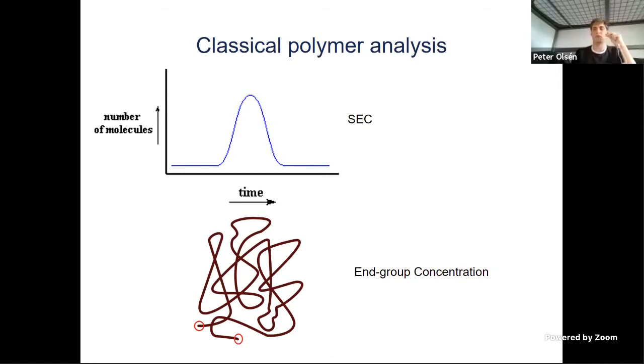So if we connect these, the question here is what is actually happening with the degraded matrix polymer during compounding and its relationship to the initial moisture content in the fiber. When we do a polymer analysis, the two main methodologies we use are either SEC, size exclusion chromatography, looking at the molecular weight distribution of the polymer phase, or NMR, looking at the end group concentration in relationship to the repeating unit. These are two very powerful techniques that give very different intel of the polymer population.